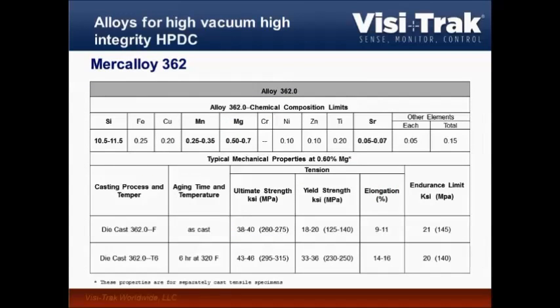So if we just have a look at, and I'm using the example of the Mercalloys here because they're probably the least known of that series, because most publications were really made on the Silafont and the Aural alloys. But we have about the same principle. So we see in the 362 type, we have 11% silicon for highest fluidity. We use the 0.3% manganese, here a relatively high magnesium level, so we get higher strength, and the high strontium addition. And now we just play with the temper here.